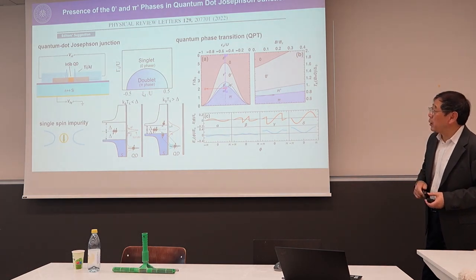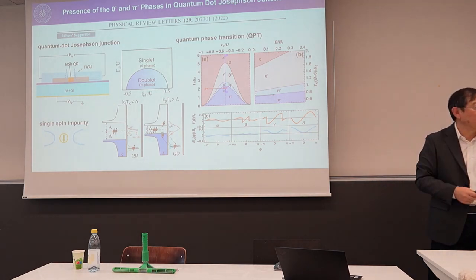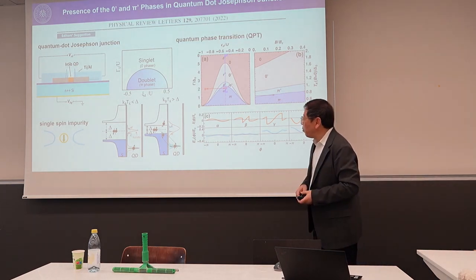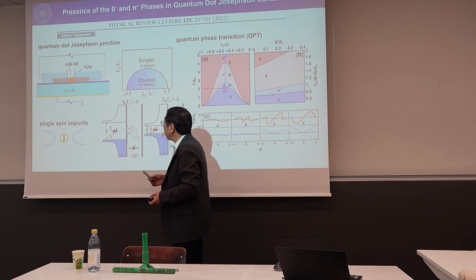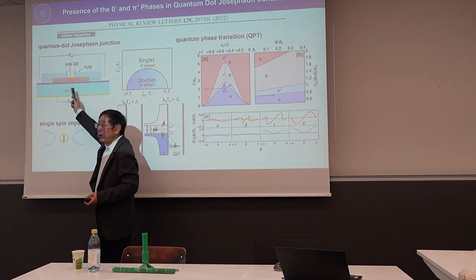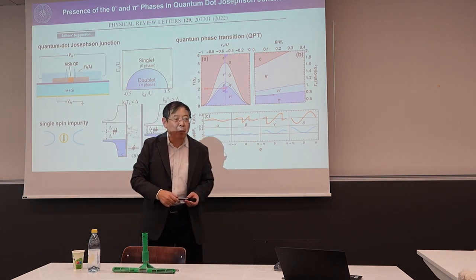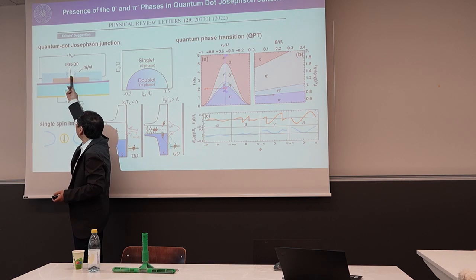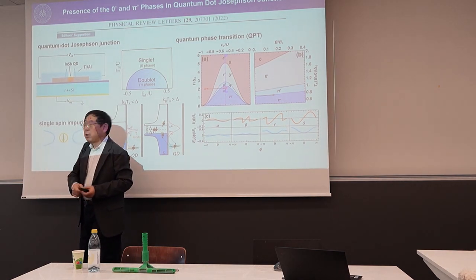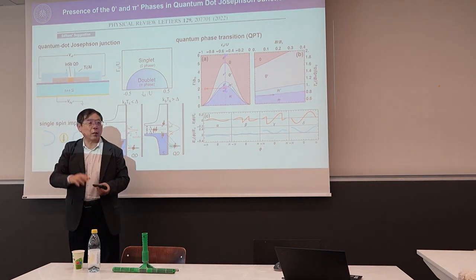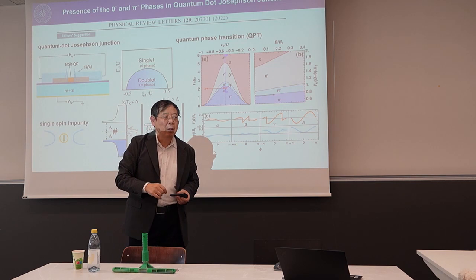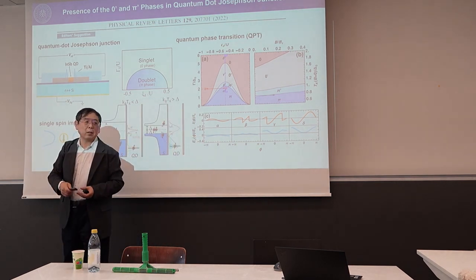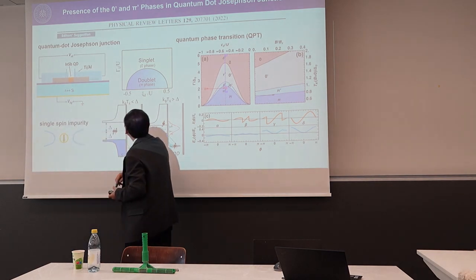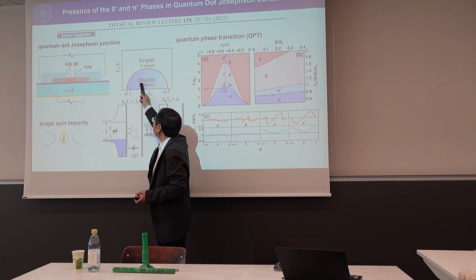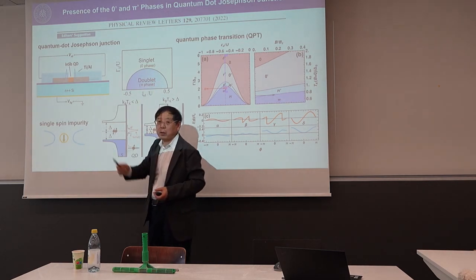Another thing we did is a series of collaborations with a Spanish group, the Gloria Palacio group, and the Korea group. We see this in a quantum dot. If we have a quantum dot and a superconductor, in this case we have a quantum phase transition. Normally we have one quantum dot with spin here. We have a zero junction, meaning these two sides form a zero junction, in the strong Kondo regime. Or in the weak coupling regime, we have a pi junction. So this structure can have a zero junction or a pi junction, and sometimes we call the pi phase the doublet state, and the zero junction case the singlet state.